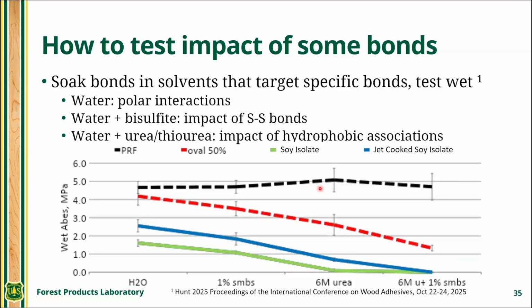I just wanted to point out there is a way to kind of address these questions of what's going on, and that would be to soak the cured adhesive, like your bond line, like your ABES specimen, in a solvent that targets a specific bond. So water targets polar interactions, and so we test wet all the time. So here's the wet strength of PRF, ovalbumin, and soy isolate that was jet cooked and soy isolate that wasn't. Then we took more of these samples dry, put them in water plus SMBS, which breaks disulfide bonds. That didn't affect PRF, but it did affect ovalbumin and the soys.